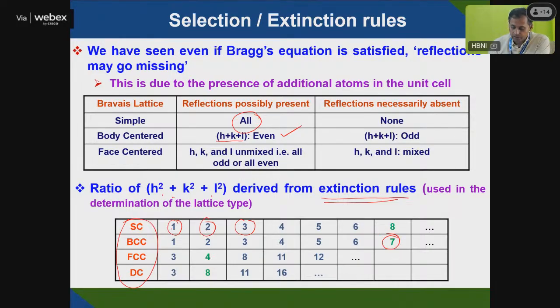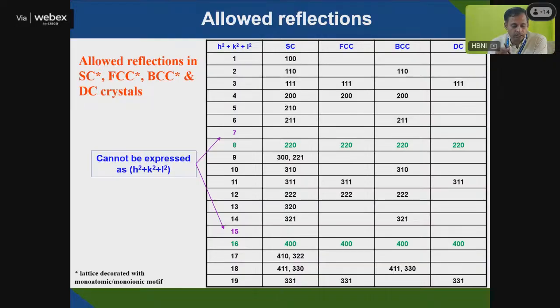Similarly, FCC gives 3, 4, 8. So all these extinction rules apply. If you see here, for H square plus K square plus L square, 7 and 15 are not possible. You can't get any plane for these. For example, if you take 1, that may be the 1, 0, 0 plane. You can get the 1, 0, 0 plane, or 0, 0, 1 or 0, 1, 0 plane, in simple cubic. For 2 it is 1, 1, 0. For 3 it is 1, 1, 1, so 1 square plus 1 square plus 1 square gives 3.